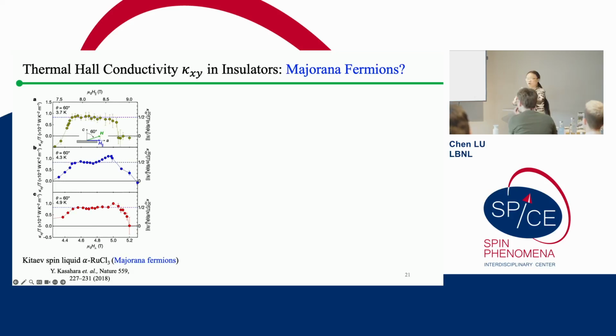One of the most famous examples, which probably a lot of the audience here already know, is the half-quantized thermal Hall conductivity reported by Professor Yuji Matsuda's group in Japan. Back in 2018, they measured one of the most well-known Kitaev spin liquid candidates, alpha ruthenium trichloride. What has been plotted here is the thermal Hall conductivity versus field taken at different temperatures. You can see that the thermal Hall conductivity indeed shows some plateau-like behavior, which they believe comes from those Majorana fermions, acting like a smoking gun for the Kitaev spin liquid.